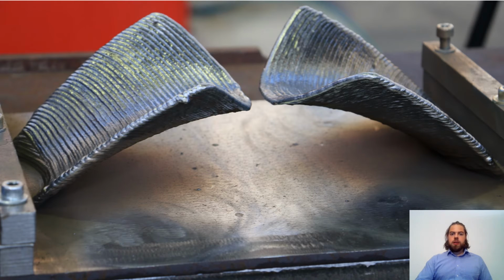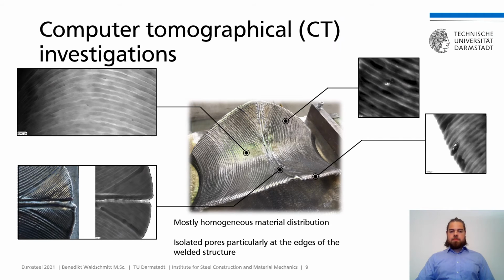The results described were used to manufacture two bridge models with a scale factor of 1:8. The picture shows the ongoing manufacturing process of one model. It was then examined for non-visible defects and for a homogeneous material application by means of computer tomographic scans. Lighter areas describe a lower material thickness. The scan data shows a mainly homogeneous material distribution, visible in the upper left image.